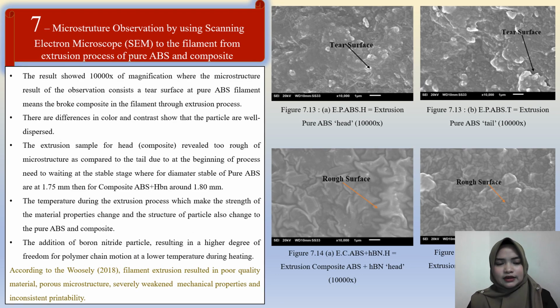For number 7, microstructure observation using a scanning electron microscope (SEM) on the filament from the extrusion process of pure ABS and composite, also at 10,000 magnification. The result shows a rough surface on the pure ABS filament and the broken composite in the filament from the extrusion process. The differences in color and contrast show that the particles are well dispersed. The extrusion sample for the head of the composite revealed a rougher microstructure compared to the tail, because the beginning of the process needs to reach a stable diameter, which for pure ABS is 1.75 mm, while for composite ABS HBN it is around 1.80 mm.